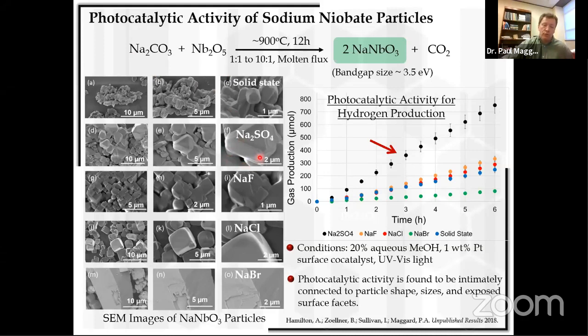And we see particle shapes which expose the 110 crystalline facets of sodium niobate versus the metal halide fluxes, such as sodium fluoride, sodium chloride, sodium bromide, where you can see predominantly cubic morphologies within each of the products here, going up in size from sodium chloride to sodium bromide, because the solubility of the sodium niobate is going down as you go from fluoride to chloride to bromide as fluxes.